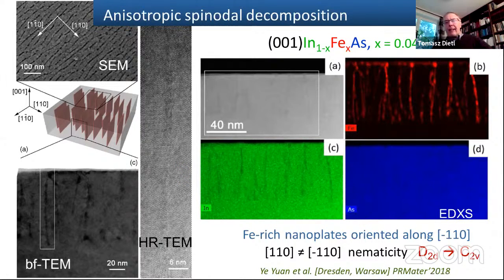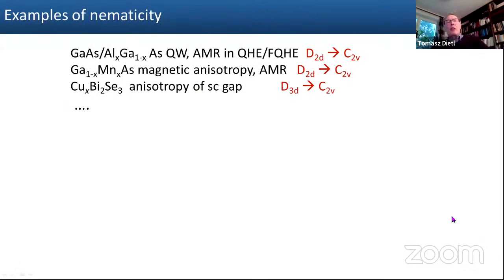We call this effect nematicity, and this effect leads to breaking of rotation symmetry. Instead of D2d symmetry, we have C2v symmetry. So we have lowering of symmetry with all consequences. For instance, if we study AMR or other phenomena, you clearly see that symmetry is lower. And actually, this is observed in many systems.